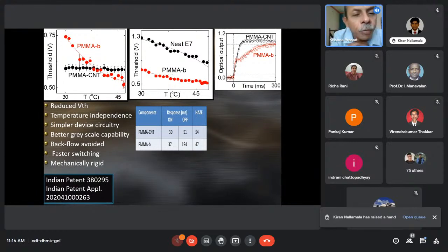So given the temperature of the device, it could easily be varying between 30 and 45 degrees. Typical temperature variations, for example in Delhi, could be 30 to 45. And over these temperatures, the threshold voltage, the operating voltage of the system, changes significantly. It means the controlling electronic circuitry now has to account for this change in threshold voltage. And because of these kinds of changes, it becomes a complex problem to design device circuitry for liquid crystals. But having such a temperature independent system is going to significantly reduce the circuitry for the system.